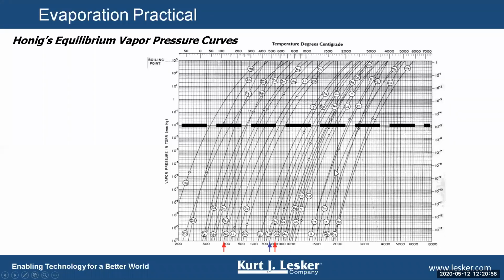The dots on these curves represent the melting points of the material or the elements. So if the melting point is below this 1 × 10⁻² torr pressure line, generally the material is going to melt and then evaporate. If the curves are substantially above this line, that means the material most likely will sublime. It's good to know this because we get many calls from people saying, hey, I'm heating my material up and it's not melting, but I'm getting rate. What's wrong? And the answer to that is nothing. The material is subliming.